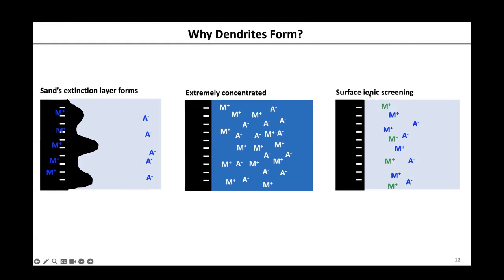Another solution is to use so-called ionic screening. We have two types of cations in the electrolyte. We have our anode cations, converted to anode metal. We have another type of cation which cannot be converted to metal because the potential required is extremely low. For example, if we plate zinc and we add some lithium ions in the electrolyte, the lithium ions will not be converted to lithium metal. So these cations will be gathered on the surface, and they don't allow the vacuum or the extinction layer to form. We call this ionic screening. With the cations there, the anions will be attracted not so far away. So these are two promising solutions.